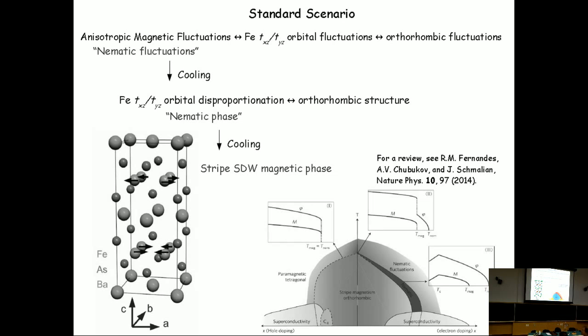Apparently. Yes. In other words, the doubling direction is parallel to the... Yes, right. In principle, it is believed that the magnetic phase transition should be joined with the electronic phase transition and the structural phase transition. But then we start seeing that they may be different. These two transition temperatures, the orthorhombic phase transition and the nematic phase transition, may be at a different temperature from the magnetic ordering temperature. But they are clearly connected. Somehow they are connected, but not necessarily by the same transition temperature. Okay. Yeah.